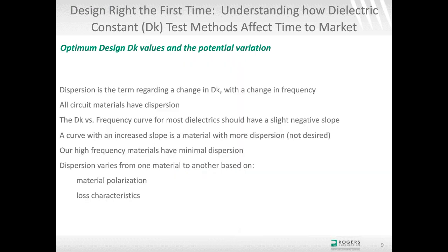There's also dispersion, and many of you are probably aware of dispersion in the sense of transmission line dispersion, that microstrip is more dispersive than strip line, and that's all true, but there is material dispersion, and what's meant by that is the dielectric constant will change with a change in frequency. And as a general statement, as you go out higher and higher in frequency, the dielectric constant will slightly decrease in the range of frequencies that we look at anyway. So microwave and lower millimeter wave range of frequencies, an increase of frequency means a slight decrease in dielectric constant.